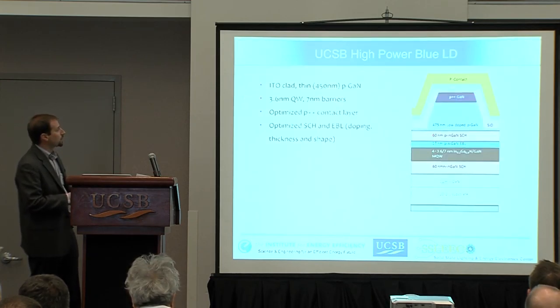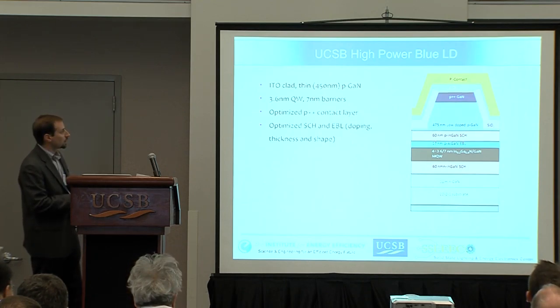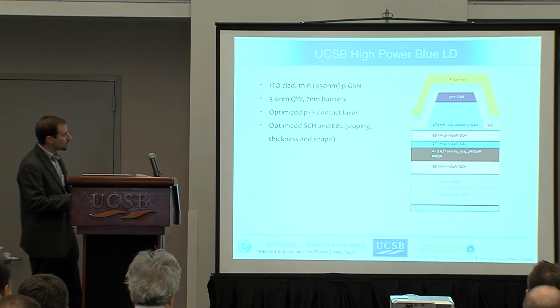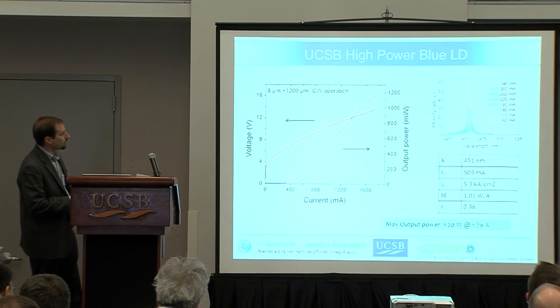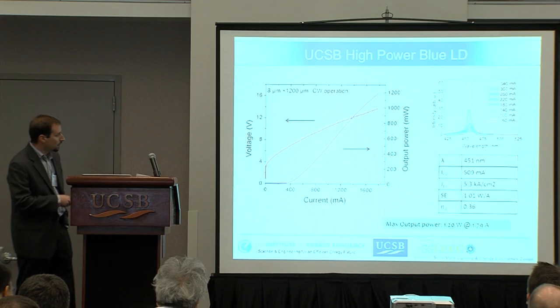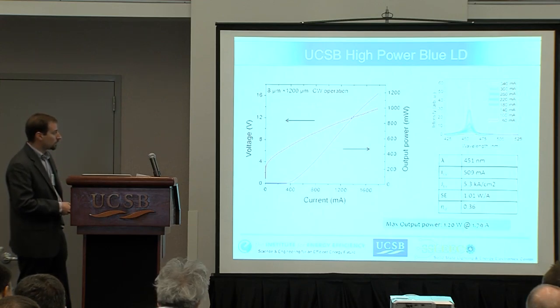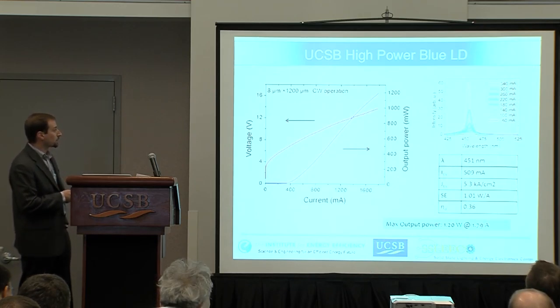We've been pushing the high-power laser diode quite a bit, working on novel structures such as using ITO claddings and contacts, and have been able to achieve — just in this last year — CW operation of devices at 1.2 watts at just about 9.3 kA/cm².